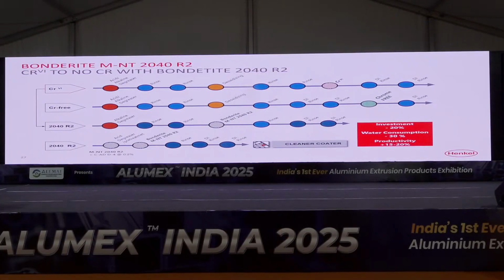Later on, some rinses, and that's all. So from the top till the end, we will have our material treated with good quality and of course with less investment, with less water consumption, a reduction of 30% more or less, and of course an increase in productivity because we have fewer stages.